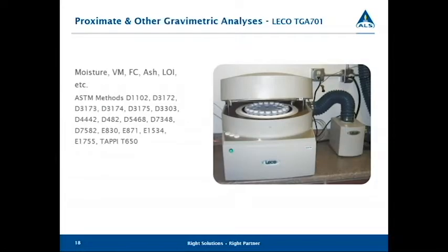The next instrument that we use is a thermal gravimetric analyzer. And this unit is specifically for fuels. And from this instrument, we can do proximate and other gravimetric analysis. Proximate is a term that includes moisture, volatile matter, fixed carbon, and ash. And then some of the other analysis that we do is loss on drying. We can also use this instrument to determine free moisture, inherent moisture, different types of loss on ignition at different temperatures. So it's a very versatile instrument.